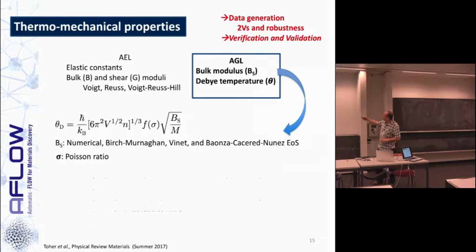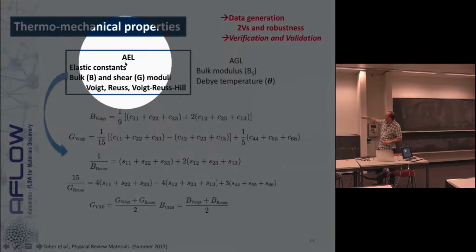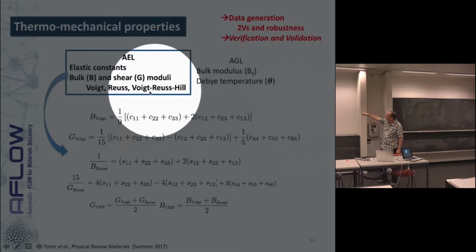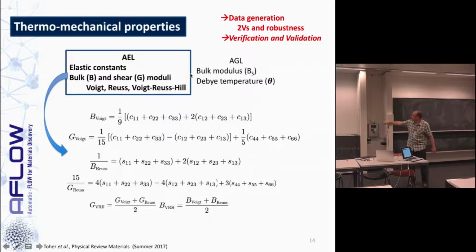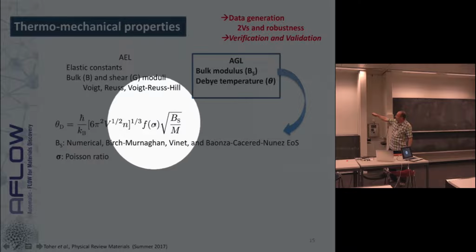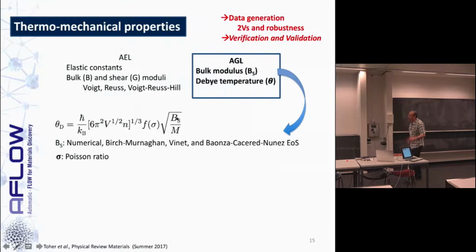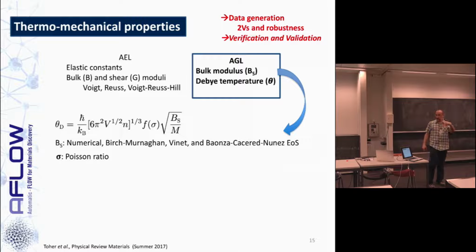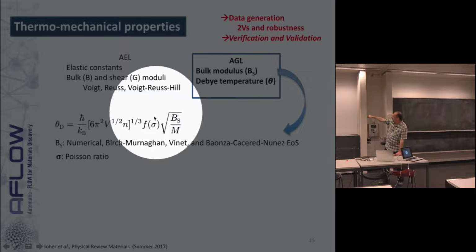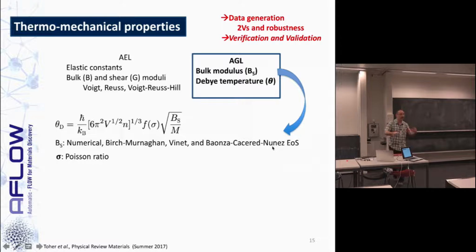For the elastic method, we simply compute the elastic constants, and then from the elastic constants compute the bulk modulus and the shear modulus, using different methodologies available in the literature. These are all different ways in which you can compute bulk and shear moduli from the elastic constants. Then we have another approach that is based on a fitting of an equation of state, which gives you the traditional bulk modulus, and then the calculation of the Poisson ratio. The function of sigma is not very variable, so you can use a single sigma for all the data. That is what we did a few years ago. When you fit the bulk modulus, you can use numerical integration, or fit to Birch-Murnaghan or to other equations of state. So this can all provide slightly different results.